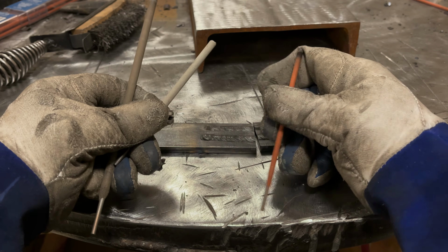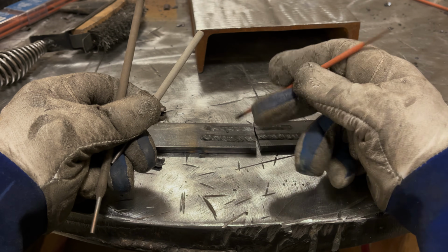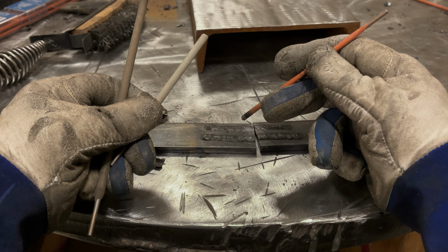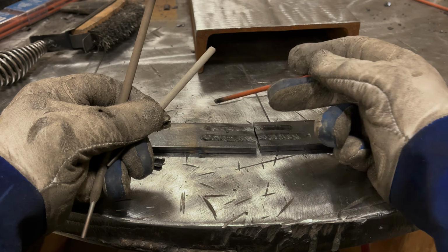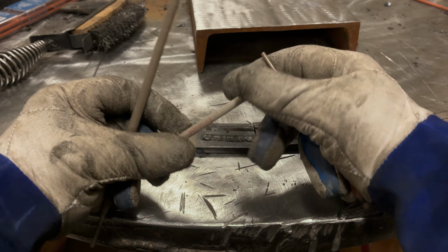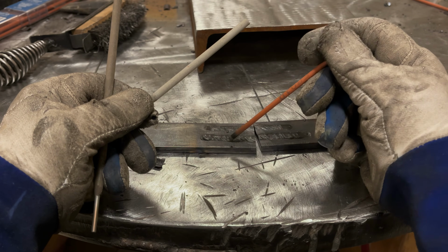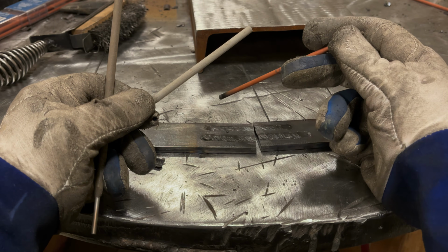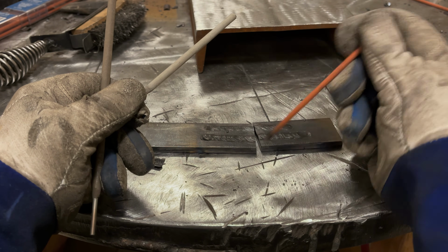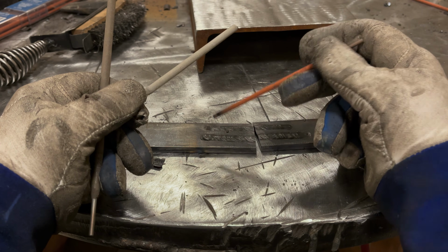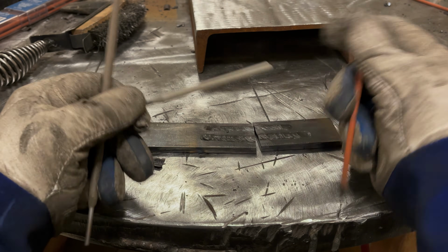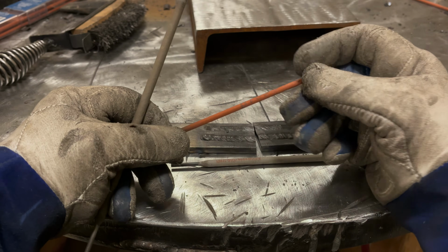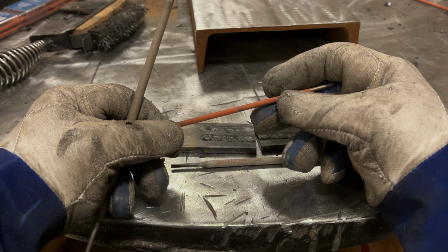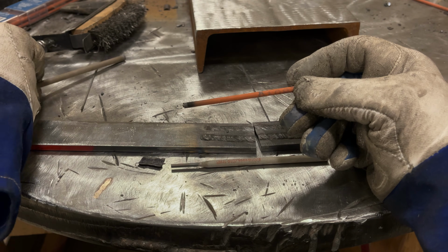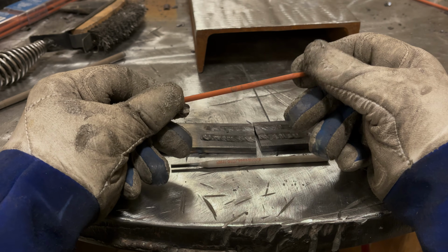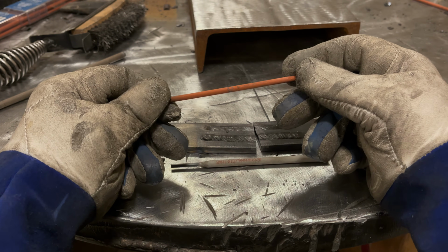Well, the 6010 rod creates an atmosphere of CO2 around the weld pool. CO2 creates a hotter weld pool than the gas that 7018 creates, okay? That is the primary difference as to why you get more penetration with 6010 versus 7018. Now, if you do MIG welding, you know that when you run 100% CO2 gas versus C25, you see slightly better penetration and a more aggressive arc with 100% CO2.